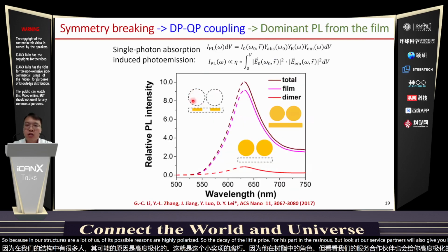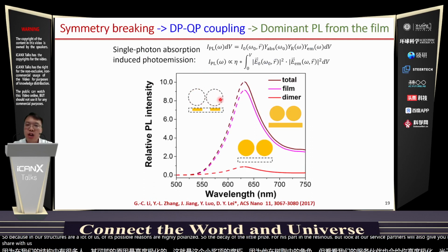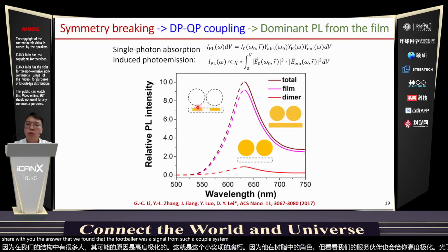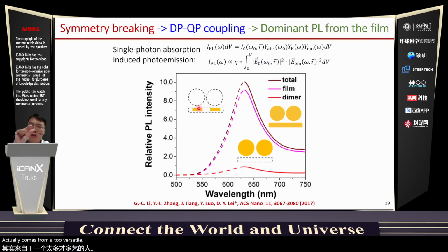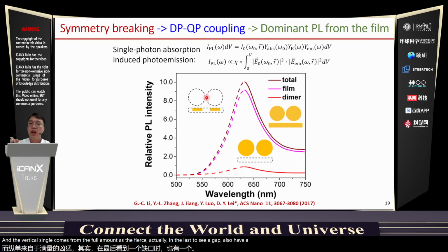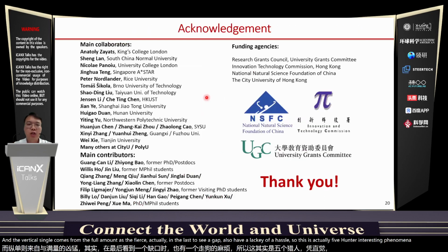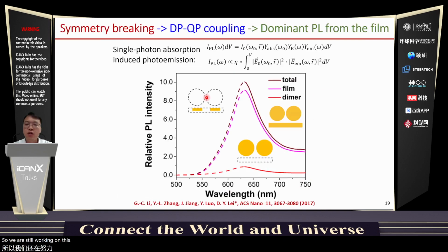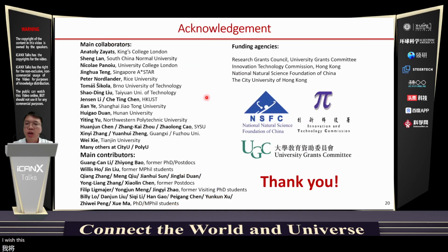The last thing I want to share with you is that we found the photoluminescence signal from such a coupled system actually comes from two very thin slabs of the metal film, and very little signal comes from the gold nanospheres, even though in the nanosphere gap we also have very large near-field enhancement. This is quite a counterintuitive phenomenon. We are still working on this, and hopefully we can extend it to the nonlinear optics regime. With this, I would like to thank you very much for your attention. Thank you.